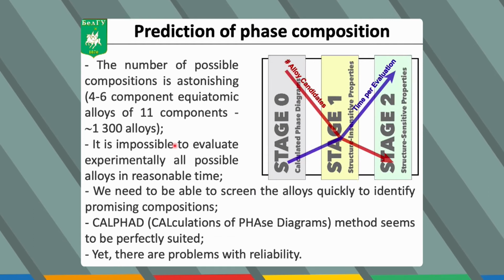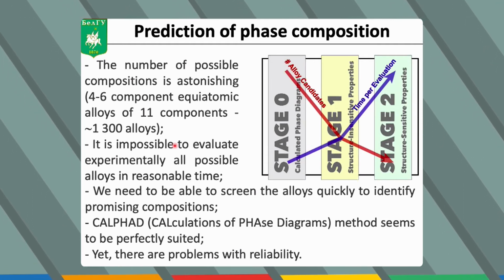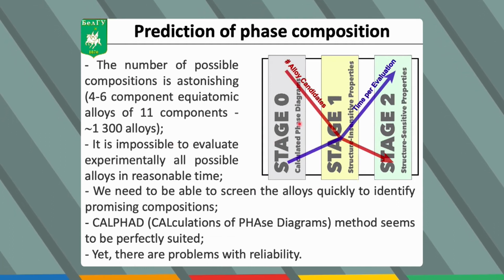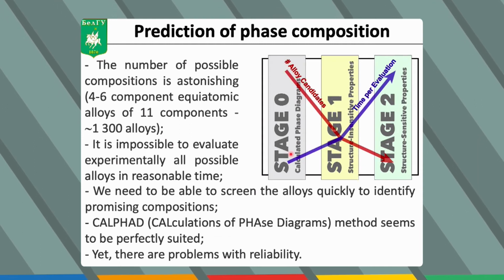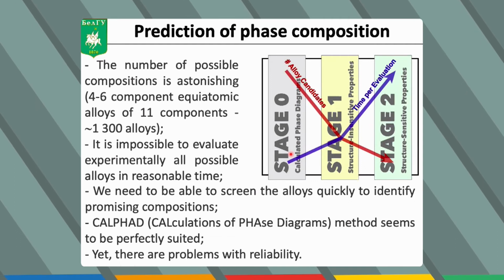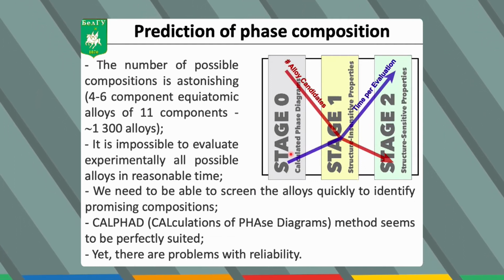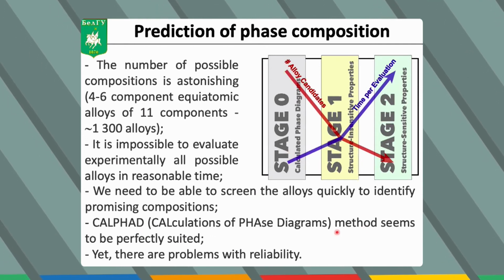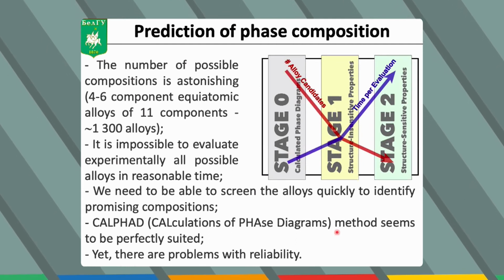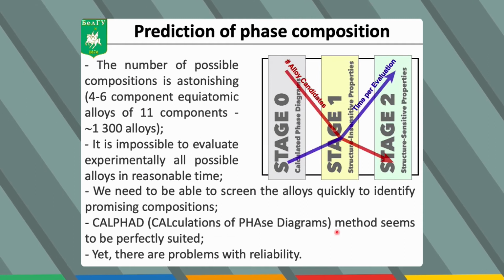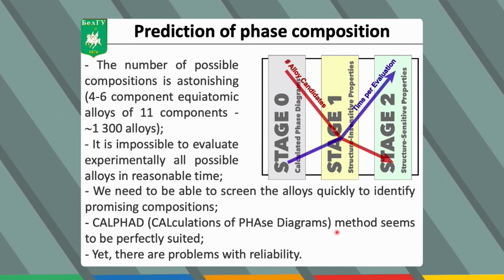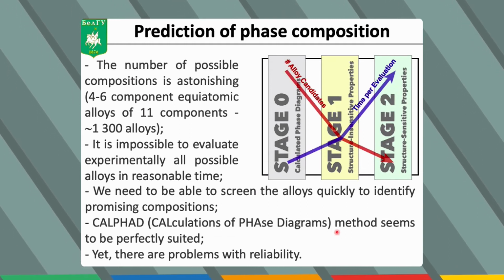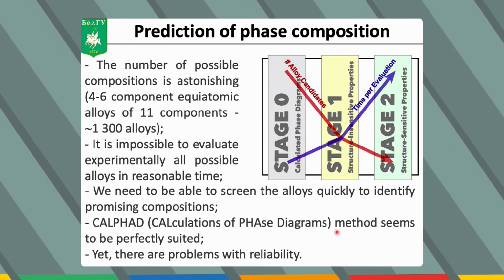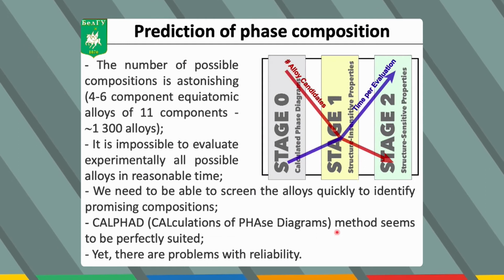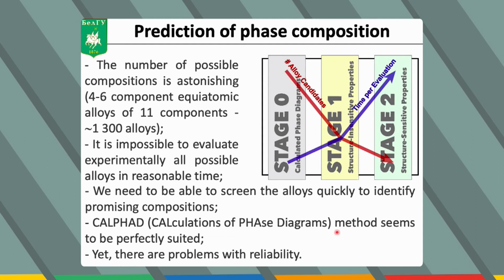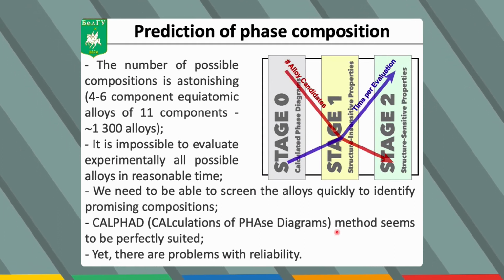And we cannot perform experiments. We cannot just study all of these alloys experimentally in a reasonable amount of time. So we need some computational tools to select the most promising alloys for future studies. And in this regard, the so-called CALPHAD approach, CALPHAD being the acronym for calculation of phase diagrams, seems to be uniquely suited. This method is based on extrapolation of the available information from binary and ternary phase diagrams. And this extrapolation makes it possible to construct the phase diagrams for complex multi-component alloys. And the huge benefit of this method is high productivity. I mean, we can get phase diagrams for hundreds and thousands of alloys in days or weeks.